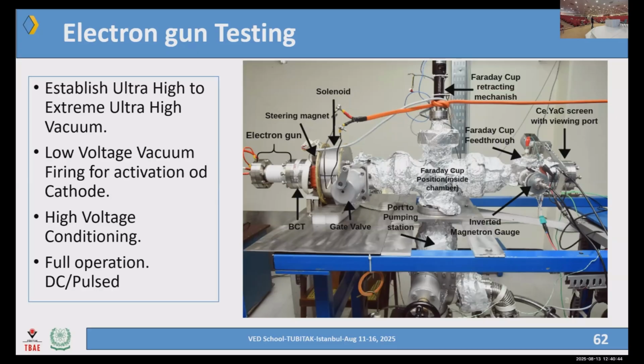So many cycles, perhaps 3-4 cycles, will get you to the point where you can switch on the ion pumps. Ion pumps can be switched on at 10 minus 4 millibars, but they will not be as efficient as they should be. Because ion pumps are sinks, they will not gather and spit out. They will gather everything. So they age very soon if they are operated at higher pressures. So ion pumps are switched on when this line is at a reasonably good vacuum.